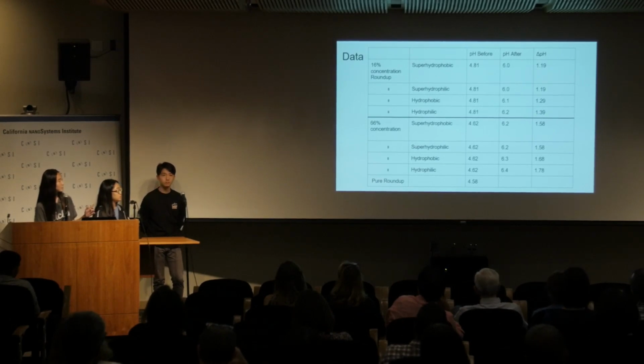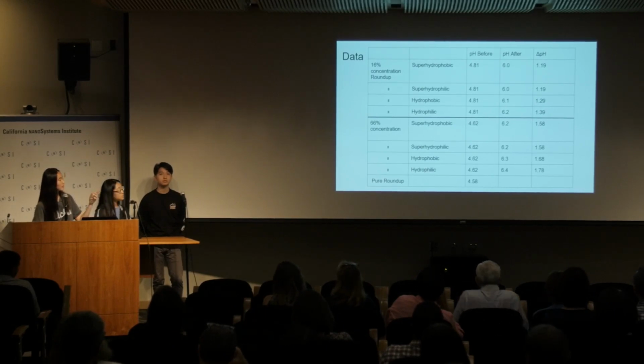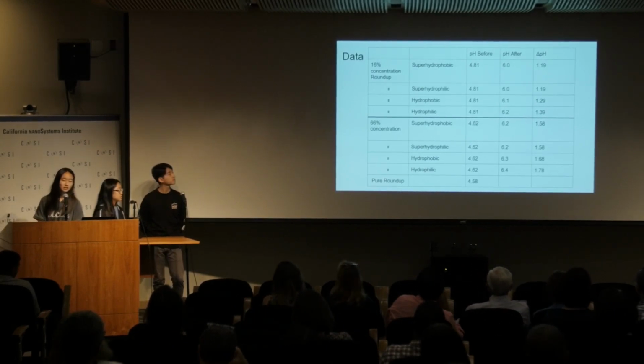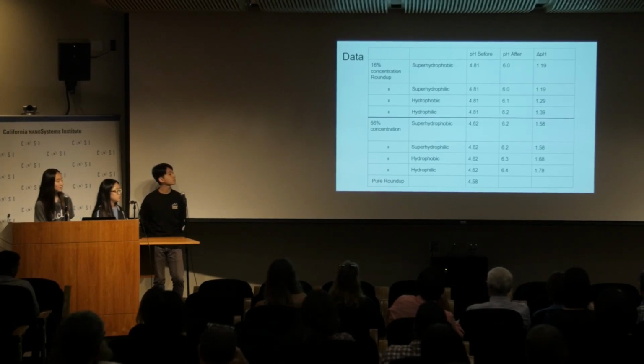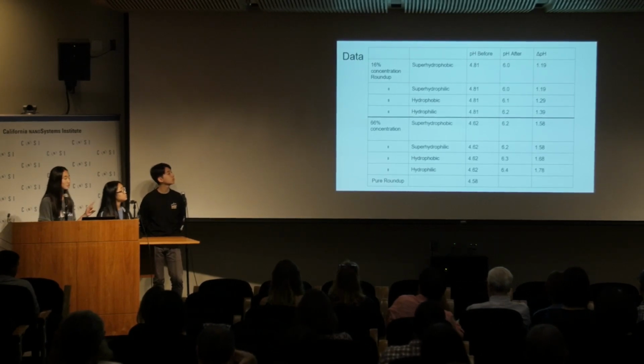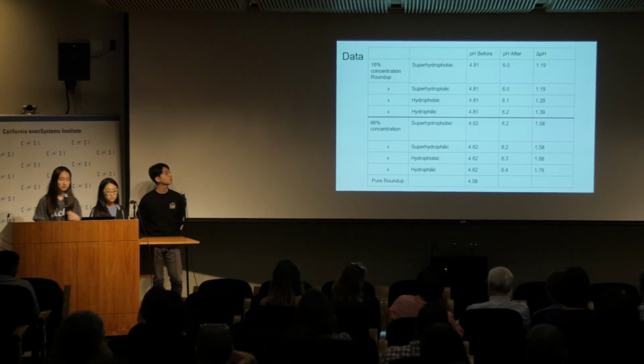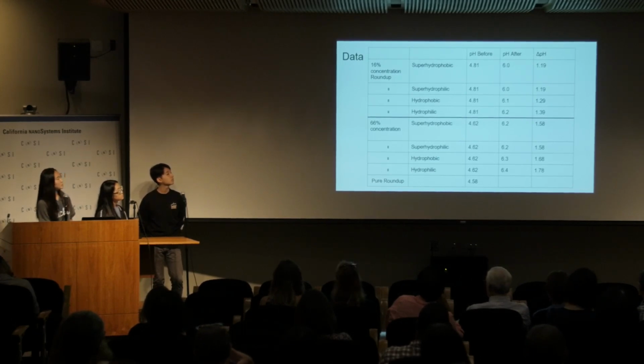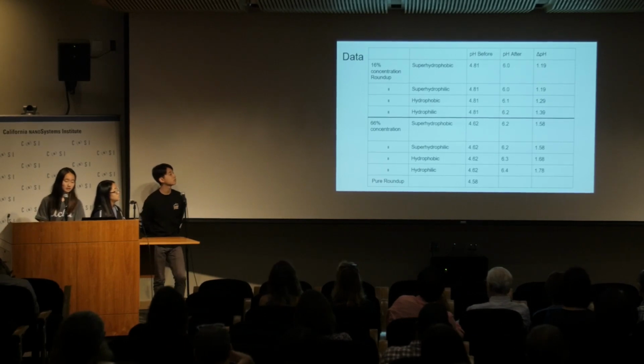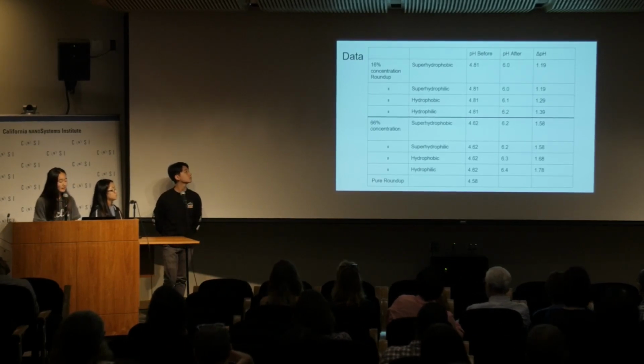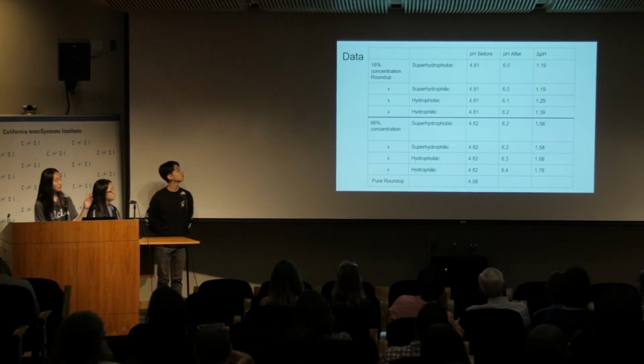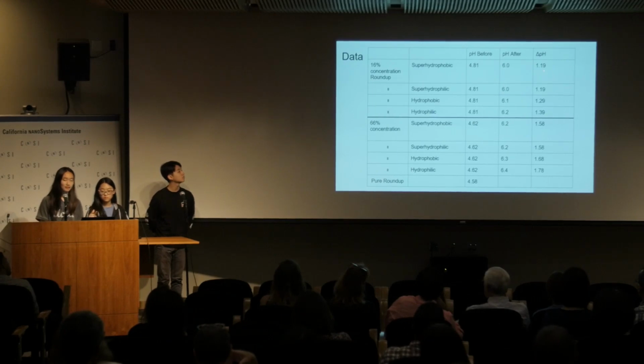And we measured pH because the pH of pure Roundup is acidic, which is 4.58. We originally planned to do 4 different concentrations, but with the limited time and the long process it took to filter the concentrations, we only did the 2 extremes, 10% concentration Roundup and 66% concentration Roundup. And the pH for the 16% was 4.81, and the 66% was 4.62. And after filtering it through the 4 different filters, we got the numbers in the middle pH column. And the last column shows the change in the pH from before and after the filtration.